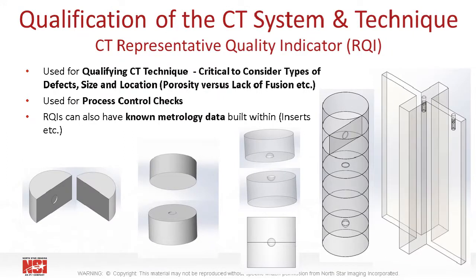Another way to build RQIs for the qualification of the CT system and technique is to either print or machine defect inserts that can be placed within a part or representative part. The placement orientation of planar defects is critical, and the build plane for the product should be considered. The defects can be either left empty or filled with representative powder or inclusion material. The benefit of the 2-part disc approach is that the RQI's features can be dimensionally verified with conventional methods.